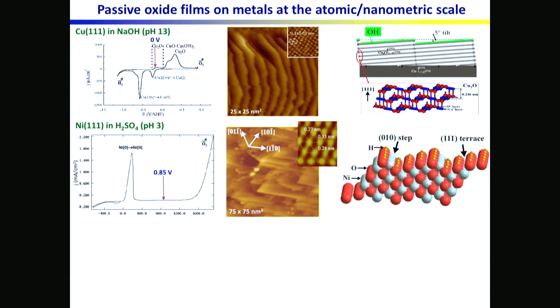So if you look at this image, you find again terraces and steps. So although again we start with a very smooth surface, so again the film, which is crystalline, is clearly not in perfect epitaxy with the substrate. It's in a tilted epitaxy with the substrate. The structure that can be locally measured with the STM is clearly, again, an hexagonal structure, and it corresponds exactly to the structure of nickel oxide, NiO, which is an oxide that crystallizes in the rock salt structure, the NaCl structure.